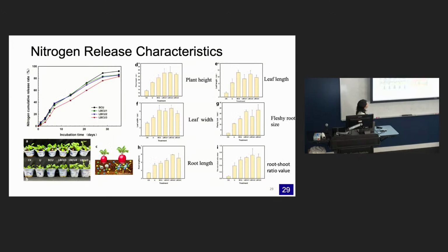Here is one of my students using radish as a plant. Firstly we look at the nitrogen release rate. You can definitely see that with this nanohybrid included, they can significantly reduce the nitrogen release rate. You can see even at 20 or 30 days, definitely good slow release. And here are some leaves and the root-shoot ratio. You can see this plant has more leaves and is in much better condition than this one, the control.